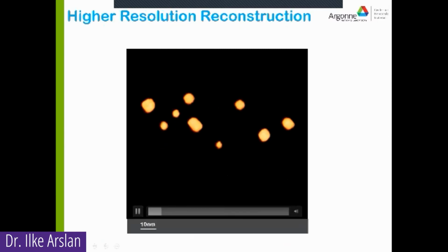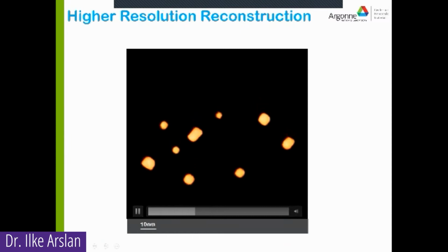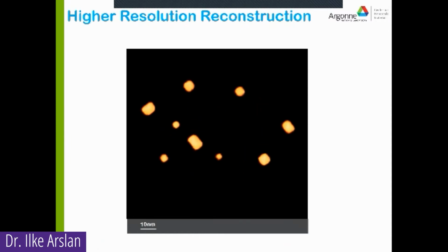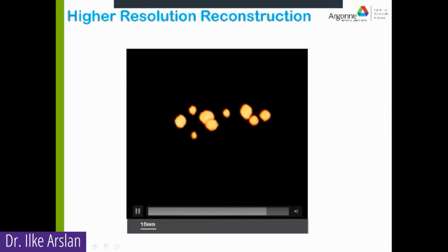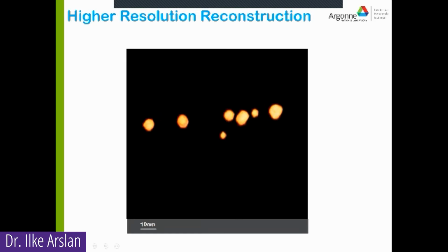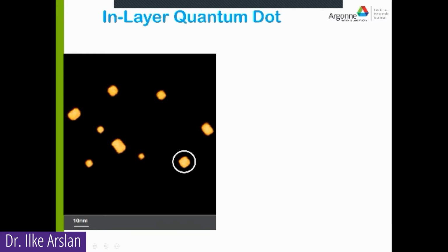And then we did higher resolution reconstructions in this area to try to figure out what was going on. If you can notice in this movie, some of them are more symmetric, and some of them are not. And this is because some of them stay as alpha tin, which is the semiconducting component that we would like them to be, and some of them have morphed into beta tin, which is what we do not want them to be. But again, the question is, why is this nanoparticle forming outside of these layers? And how do we get to stop it?